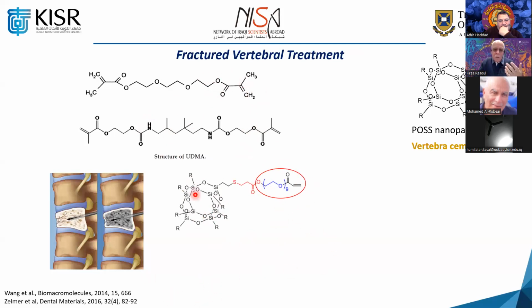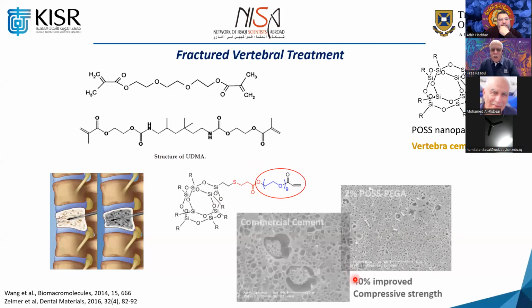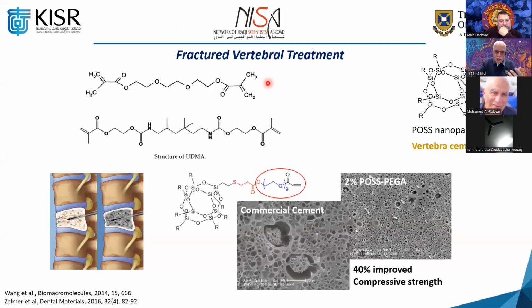Of course, when we combined all these three together and we polymerized it, then we looked into the commercial cement, and then compared it with only using 2% of this POSS. You could see there is almost 40% improvement in compressive strength.